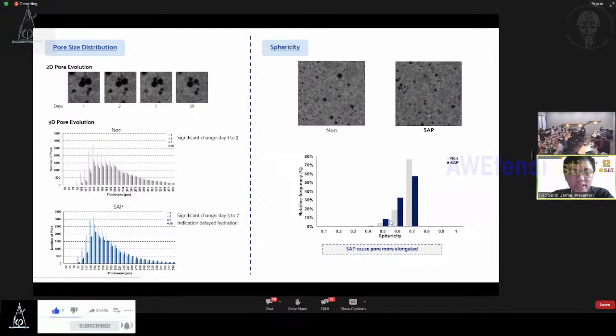From X-ray CT, we can quantify pores in 3 dimensions. In non-SAP specimens, significant change occurs from day 1 to day 3, but in SAP specimens, significant change occurs from day 3 to day 7. This indicates delayed hydration from some water still inside the superabsorbent polymer. We can also observe the sphericity of the specimen. SAP causes pores to be more elongated, following the SAP structure.